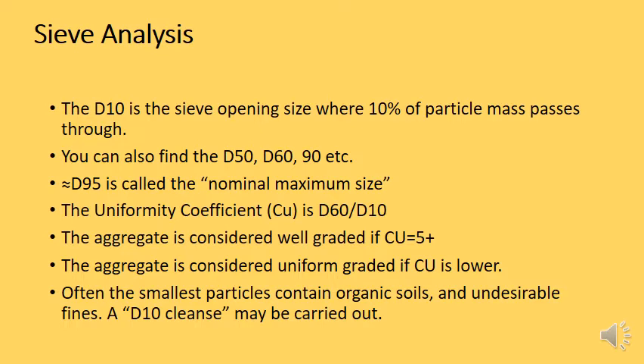It would be 10. Now, an aggregate is considered well graded if the uniformity coefficient is more than 5. If it is lower than 5, it is considered uniformly graded or poorly graded. So remember, the way to determine if an aggregate is well graded or poorly graded is not just from looking at the curve on your plotted graph of the sieve analysis. There's actually something called the uniformity coefficient, and this is just a stock standard way of determining if it's well graded or poorly graded.